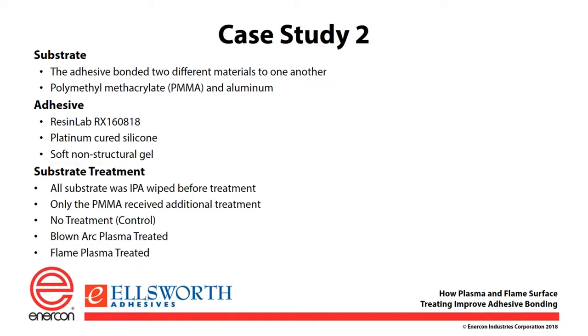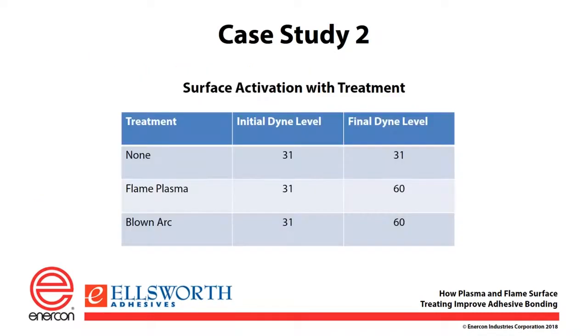Only the PMMA, so the polymethyl methacrylate, received any additional treatment. The control in this case had no additional treatment on the polymethyl methacrylate, and then once again we did blown arc plasma and flame plasma. Before treatment, the PMMA had a surface tension of 31, and after treatment you can see that flame and blown arc both took it up to 60 again.